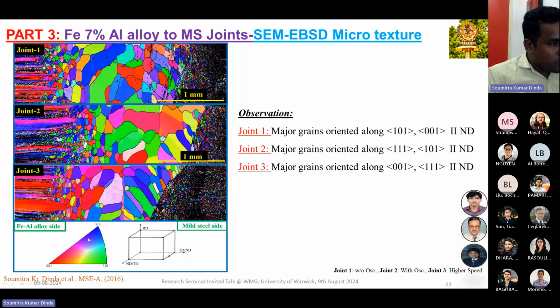This is the inverse pole figure showing the 001, 101, and 111. This color coding will help us understand which type of grains are oriented along which direction. Both mild steel and FeAl are BCC in nature. In case of joint 1, we can find grains oriented in all three directions, but the majority of grains for joint 1 are oriented along the 101 and the 001 direction parallel to the normal direction. In joint 2, we get the 111 and the 101. So in case of a BCC crystal, if the grains are oriented more along the 111 or 101 direction, then it will give more mechanical property before going to fracture.